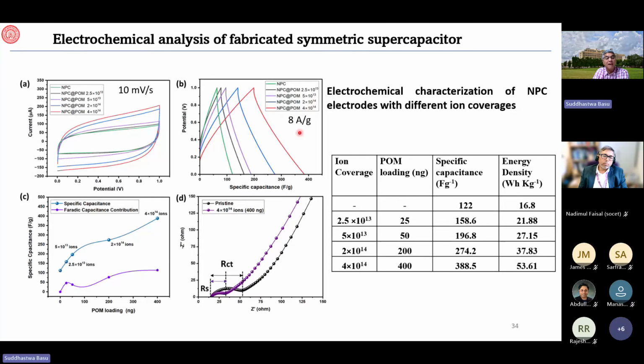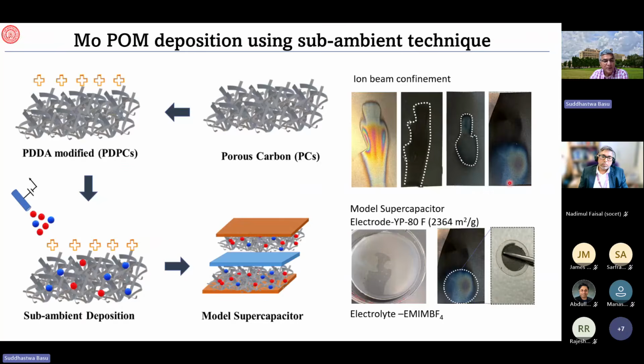So we could get about 8 ampere per gram of supercapacitor performance by POM, polyoxometalate tungsten oxide, as we are showing you. And the performance of supercapacitors at 10 millivolt per second scan rate is shown here. This is the potential versus specific capacity, 8 ampere per gram. And the table shows the performance. When we put in an ion coverage, we can count the number of ions. You can see the number of ions 2.5 times 10 to the 13, and we increase it. The POM loading in nanograms, how much of the polyoxometalate was deposited, and the mole number. We have a specific capacity of 388 farad per gram and about 53 watt-hour per kg. And that's what we have achieved, a supercapacitor, which has been published, as I said, in Small.